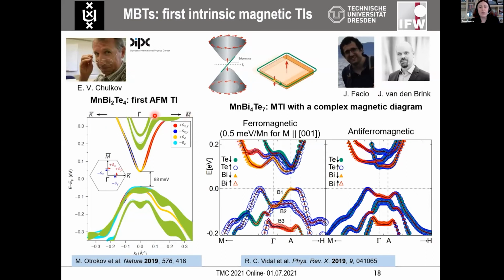So if 124 should be an antiferromagnetic topological insulator already, for 147 different possibilities become feasible. The energetic difference between different magnetic ground states becomes smaller, and one could imagine a scenario in which this compound becomes ferromagnetic or antiferromagnetic, giving an antiferromagnetic TI or a Weyl semimetal. While if the idealized composition is already prone to such flexibility, it's very well possible that the disordered models will provide an even larger playground for coupling different magnetic ground states and the topology, if we will be able to, first of all, discern the value of different factors, and second, to control the samples so well that we can deliberately produce these different stoichiometries.